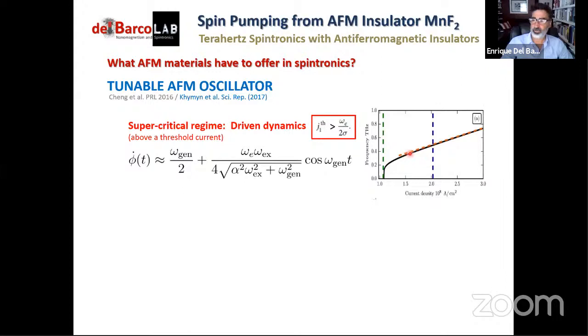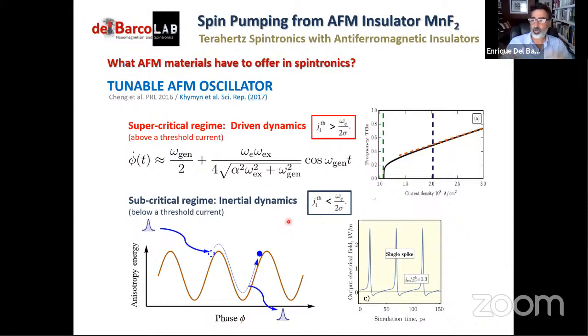And you can also tell that this frequency can be tuned over a very broad range of frequencies, from 0.2 to 0.8 here, but you know, you can go farther away. And then of course you can change the slope of this curve by changing materials, etc. But it's also interesting to be in the subcritical regime, in which the system will just follow some inertial dynamics. It's basically the first Newton law, right?